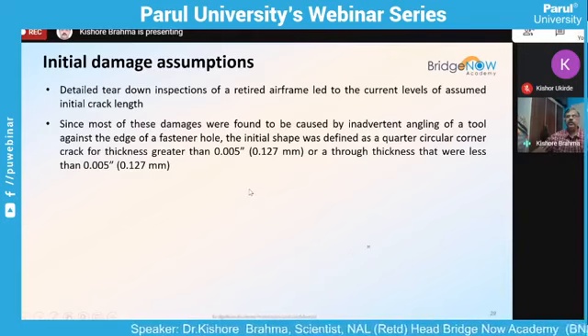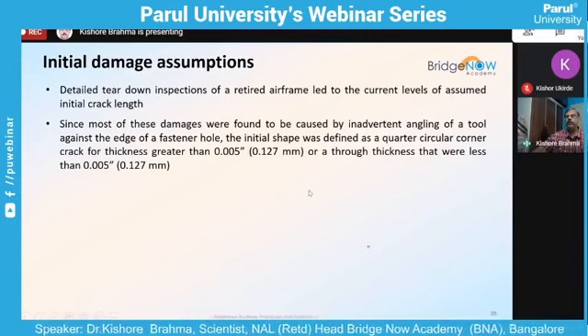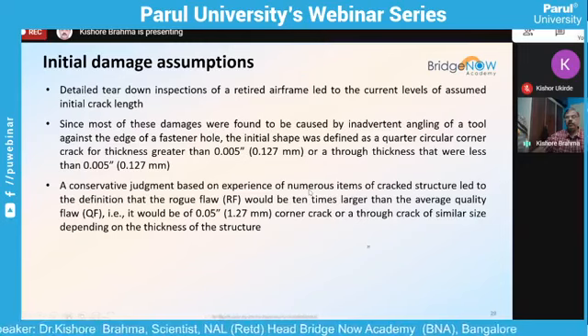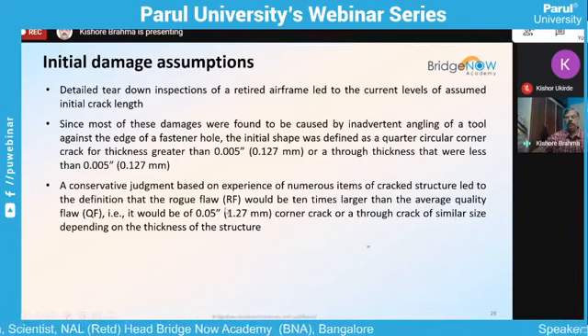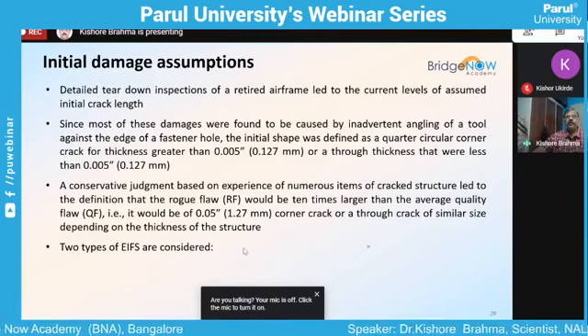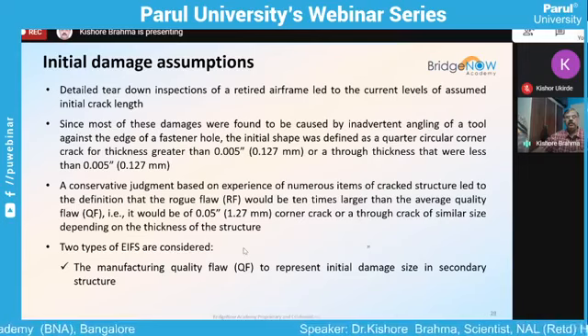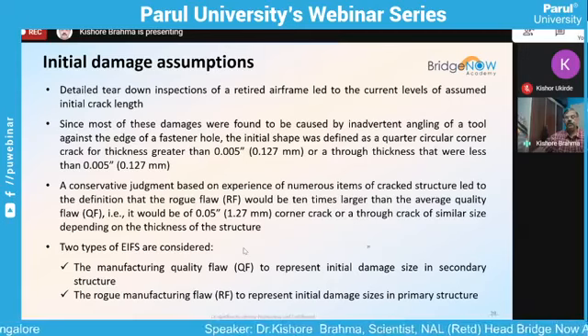Based on that, they found that the majority of parts and holes can have a 0.005 inch size, 0.127 mm. This is called the quality flaw. They also thought of a rogue flaw, which may occur in the process, which will be 10 times the quality flaw. If the quality flaw is 0.127 mm, the rogue flaw will be 1.27 mm. So there are two types of equivalent initial flaw size considered: one is the manufacturing quality flaw, to represent initial damage size in secondary structure, and the other is the rogue manufacturing flaw, to represent initial damage size in primary structure. I will explain that in a subsequent slide.